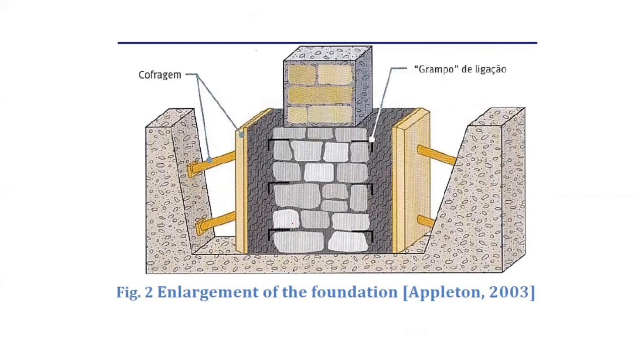We can't blindly go for concreting or cement plaster anywhere, because in one study we observed that they had an earthen wall and they did cement plastering. What happened is that the earthen wall absorbed the water while the cement plaster work was being done, and after a few months the cement plaster completely fell down. The reason is that bonding between the two is not possible.